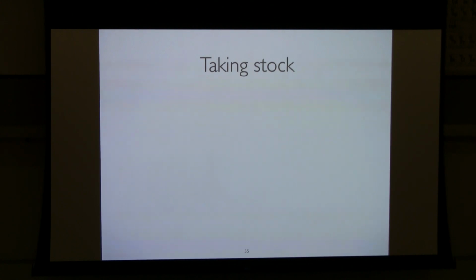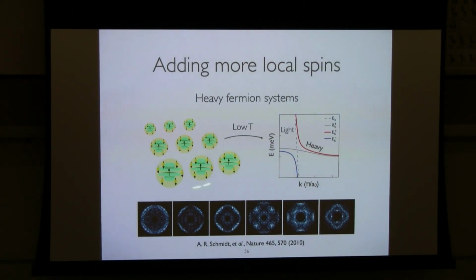Where does that get us? My motivation in trying to build this system in the first place was in part to try to understand some bulk material, or to get some intuition for some bulk material. And one type of material is one that has an array of effective magnetic sites embedded in a metal, and these sites are coupled to each other and coupled to the metal, and it can result in a set of bands that are very flat, where energy is almost independent of momentum, and as a result, it looks like the objects that move through this are very heavy. They don't have a lot of kinetic energy, and so these are called heavy fermion systems. And so many heavy fermion systems occur in these sorts of so-called Kondo lattices.